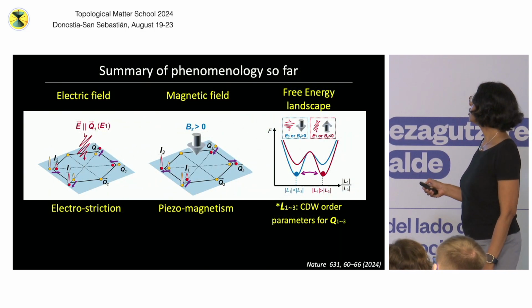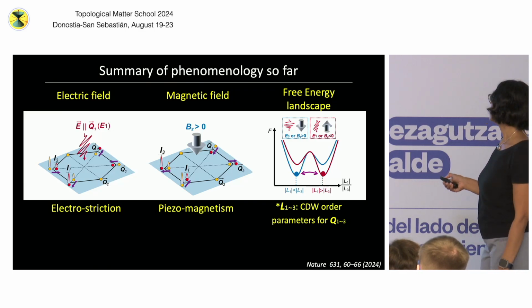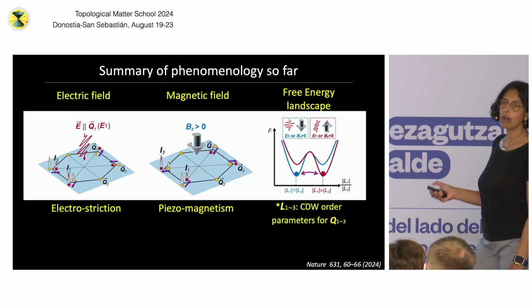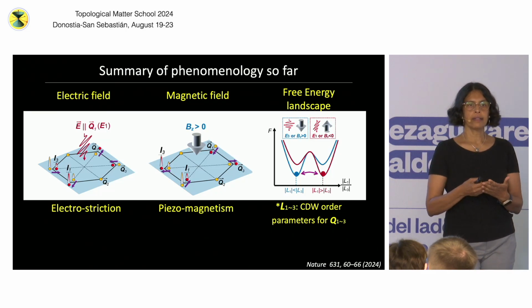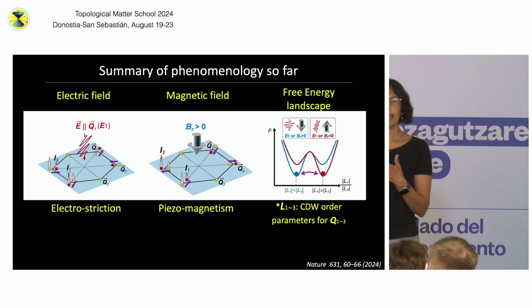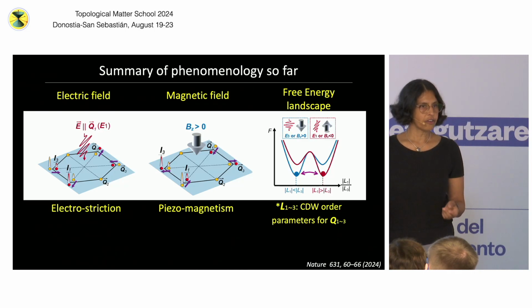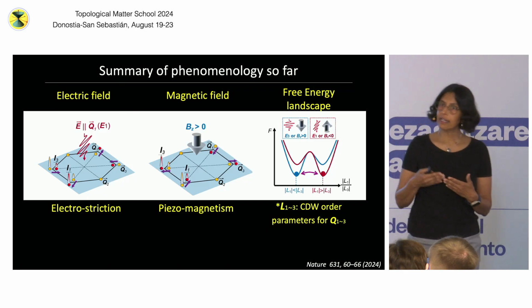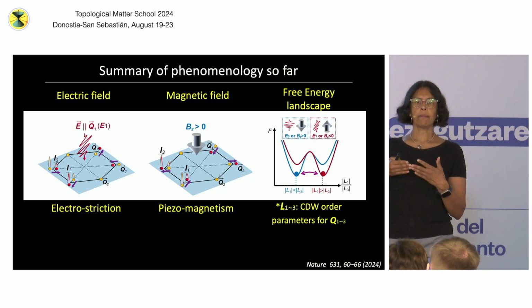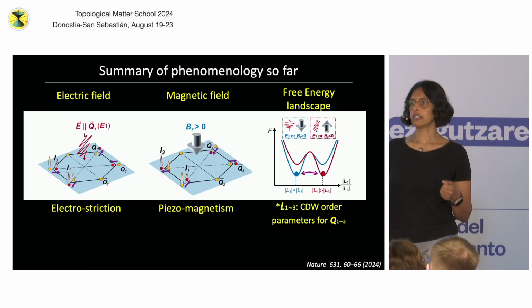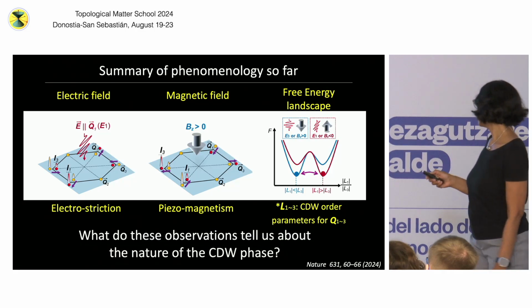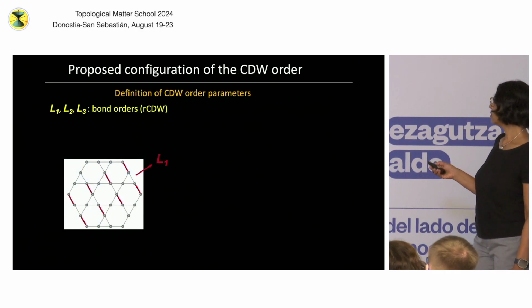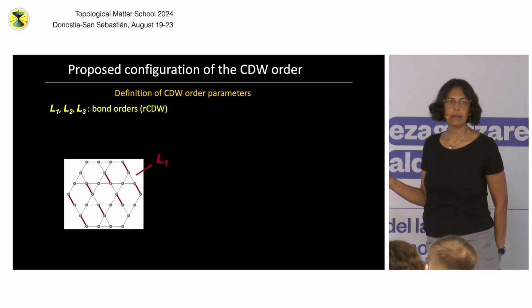So we did a combination of light and magnetic field studies. With this combination, we were able to show that the charge density wave intensity actually encodes real information on the strength of the order parameter in a particular direction, and that this CDW intensity can indeed be manipulated with a magnetic field. We proved that that's a real thing by looking at these lattice distortions that accompany the CDW intensities. Then we worked with our collaborators on this in the paper, so I don't want to go too far into it because I want to tell you about the dynamics.